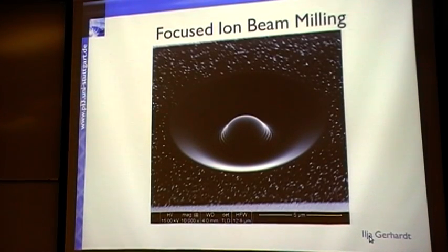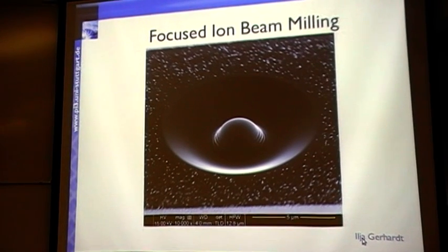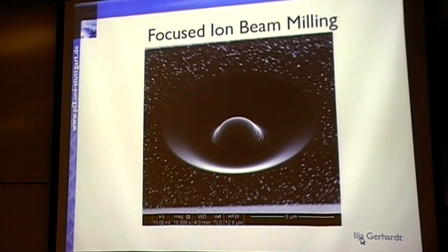So this is basically what we do in our labs. We try to find a way, a little bit like the Hanson group, and also like other groups, for example in Ulm currently, to design such a structure, such a solid immersion lens, with the focused ion beam. Basically, this is a picture from an electron microscope, and there we have a single NV in the center here, and then there's such an ion beam structure, or a milled structure, around it. It's always crucial because there's some residue here, and you really have to be very, very perfect to get rid of all the spherical aberrations.